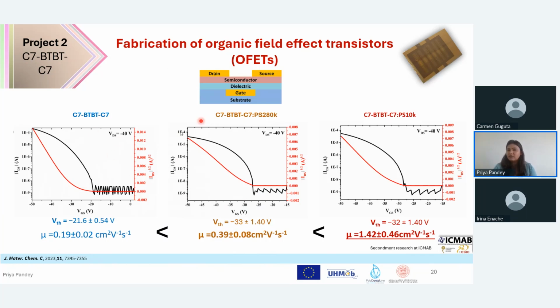I tried different configurations, different channel lengths, and different weights of polystyrene using a blend with the C7, and obtained this observation that a blend of my C7 molecule with PS of 10,000 grams per mole weight actually has the highest mobility value. And if you see it closely, in the previous slide I mentioned the expected mobility value, it actually matches quite well with the expected, and it's very good in terms of organic molecular semiconductors. So with this molecule, we have obtained these different kinds of transistors and found the best transistor and conditions. And of course, more details are available in this paper that I have mentioned over here.